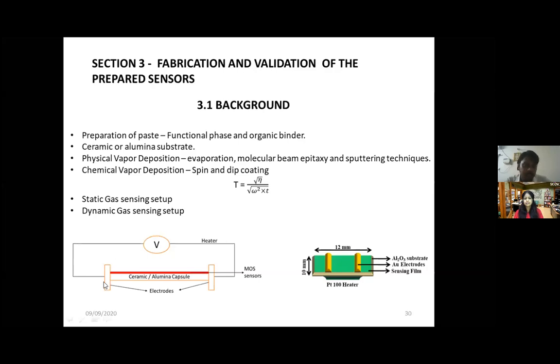And this is the working diagram of the sensor here. So the ceramic or alumina substrate, above which the sensor material is coated, and we thermally evaporate electrodes on both ends. This is the gold electrode. This is the lithographic process. We mask every other region so that the gold is evaporated and deposited only on these two regions. And there is another component present here, PT100, which is used to increase the temperature so that the chemoresistive sensor would work. So this is the fabrication procedure.